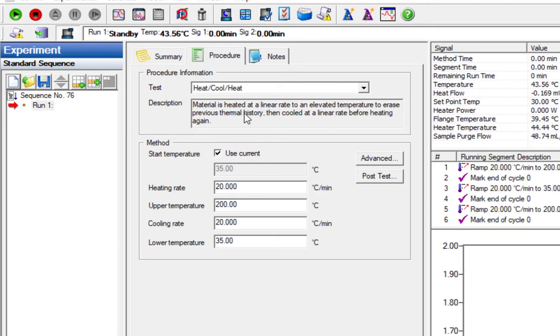One thing you definitely need to do if you don't have any information about your sample is you need to run a TGA, and the TGA will give us our degradation temperature, because we don't want to degrade samples inside the furnace because it dirties it up, and the furnace is very sensitive to any changes, including stuff being deposited on the furnace because you degraded samples inside. Degrading samples inside hermetically sealed pans can also cause them to pop open if they're pressurized too much by the gases released. And if that happens and sample gets all over the furnace, then we could have a significant downtime as we have to clean it out and recalibrate the instrument, which takes most of a full day.